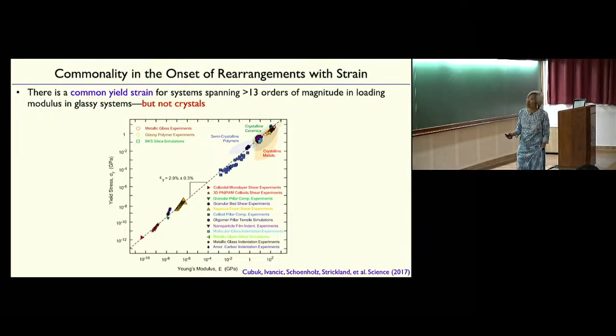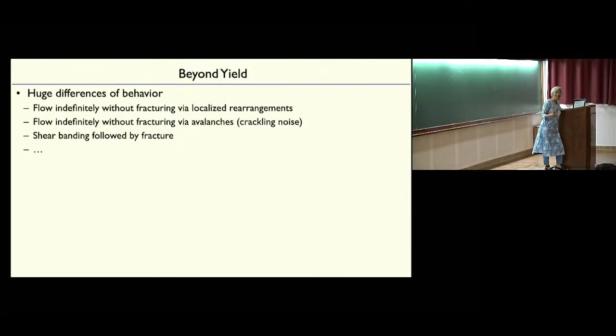The other thing that you see is that if you look at the magnitude of the yield stress versus the Young's modulus, that again is very tightly distributed around a yield strain of about 3% for all of these different systems. Look at crystals, they're all over the place. But for disordered systems, they're all about the same. And again, that's this emergent universality of behavior. It's interesting because the definition of a dislocation is universal for all crystals. But if you look at how that translates to plasticity and elasticity, you're all over the map. But even though the definition of softness is not universal, once you look at the behavior, you find things that are universal.